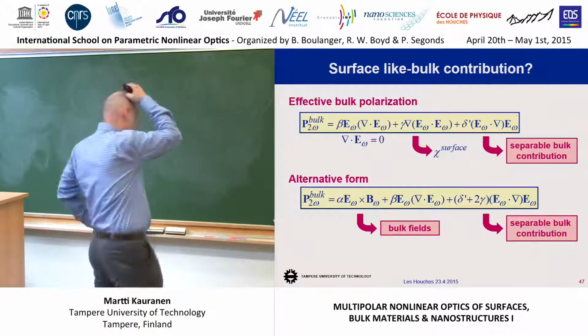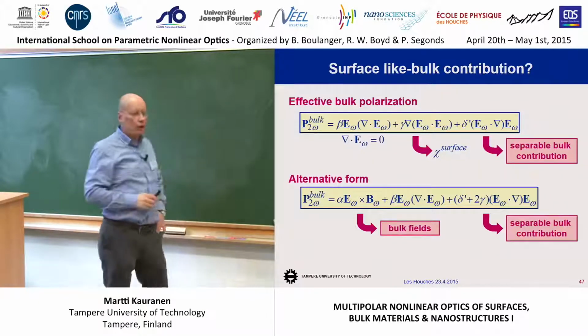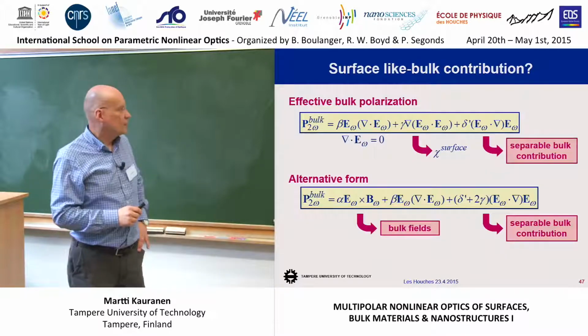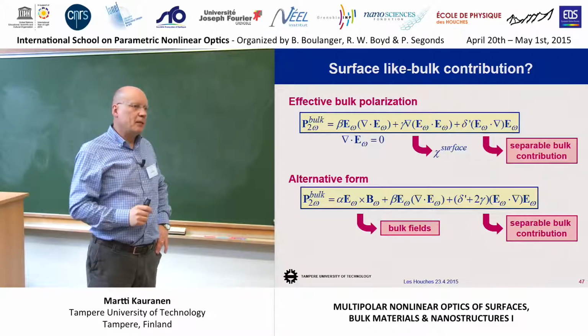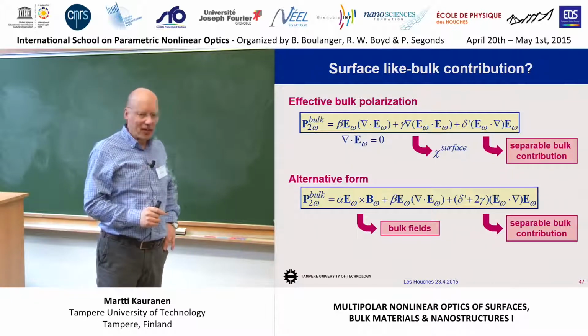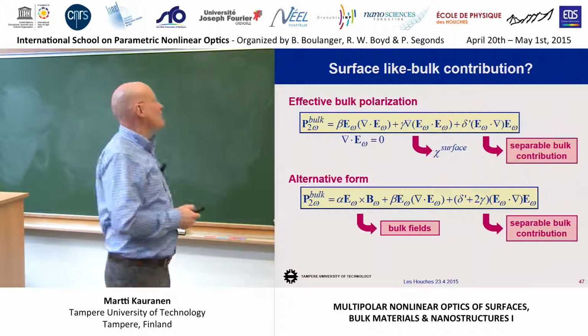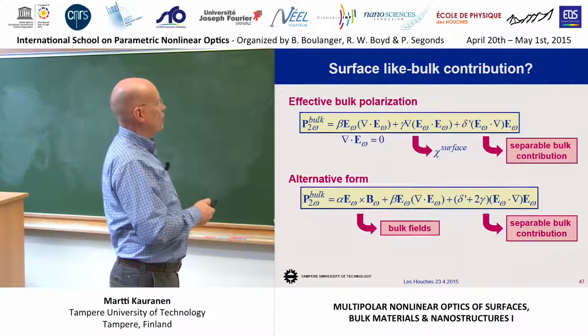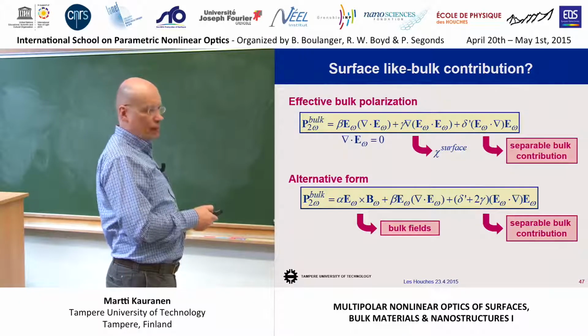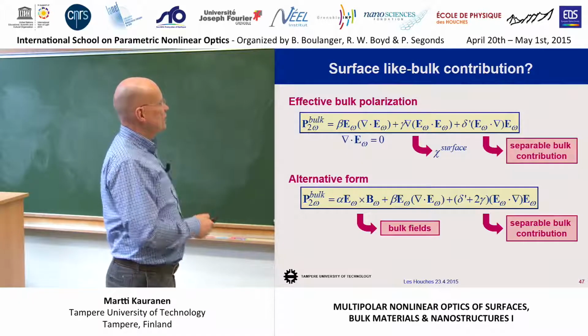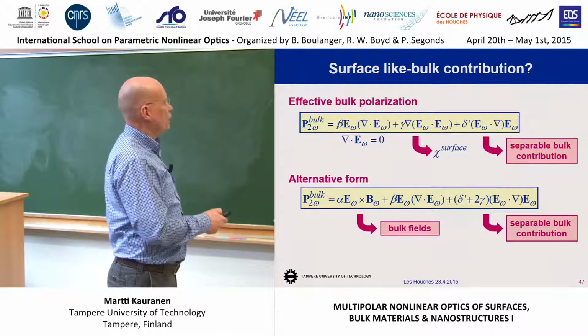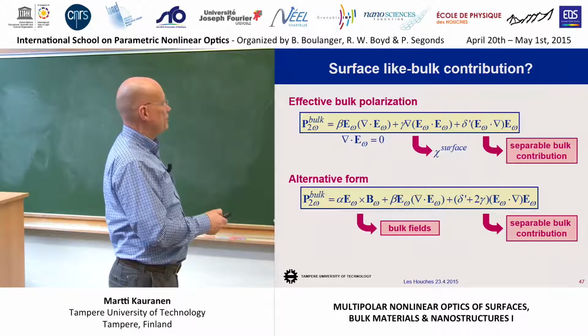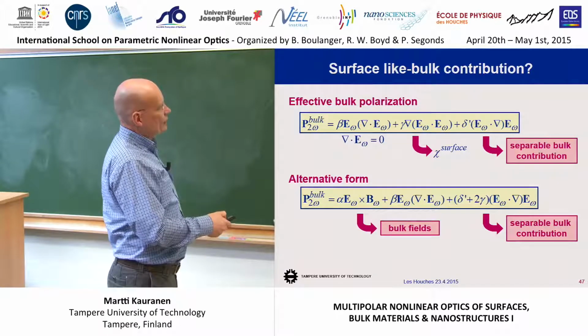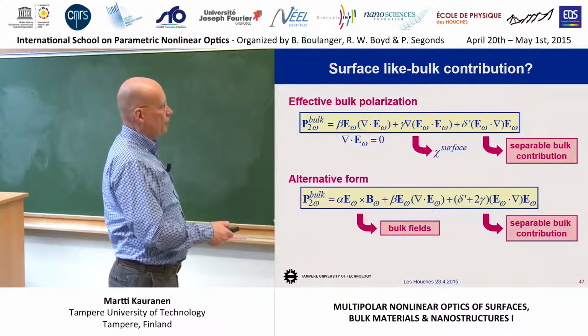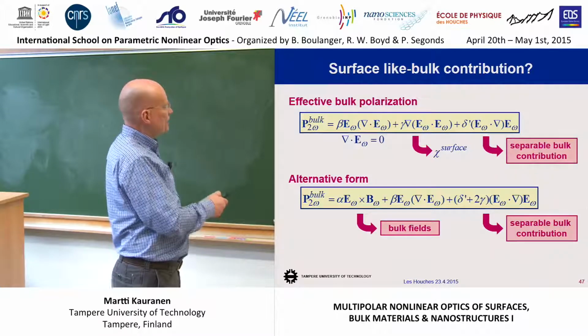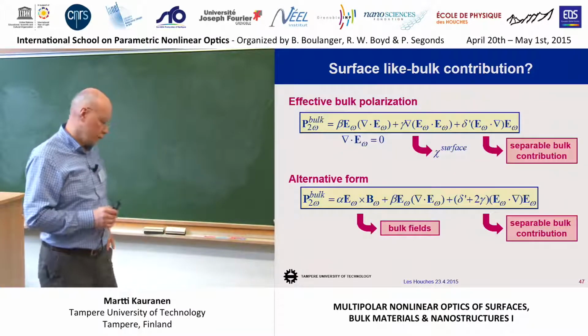Okay, I'm almost at the end. Now some of the open questions and challenges, some things that bother me actually a lot, really a lot. This is the expression for the bulk polarization in terms of these beta, gamma, and delta prime parameters. There's this old paper that argues that gamma behaves as an effective surface response, and delta prime is this separable bulk contribution. And this is the form for the effective bulk polarization, which is